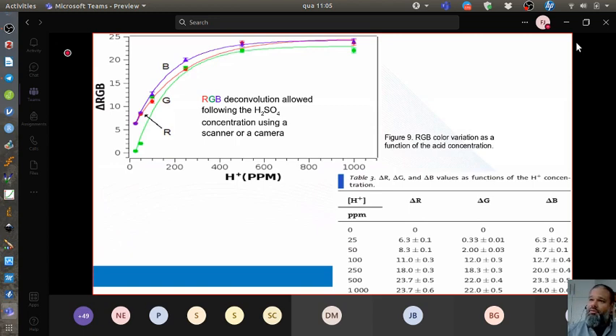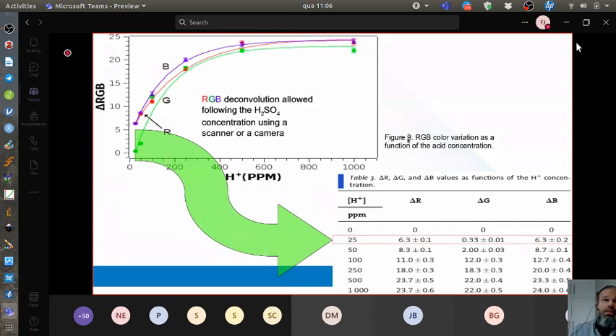Okay, when we did that, we perceived that between 25 and 500 ppm, this material is able to detect the variation of the concentration of the sulfuric acid by changing colors. Among them, the blue and the red channels are the best. So we use these two channels to follow the changing of the concentration of sulfuric acid in this case.